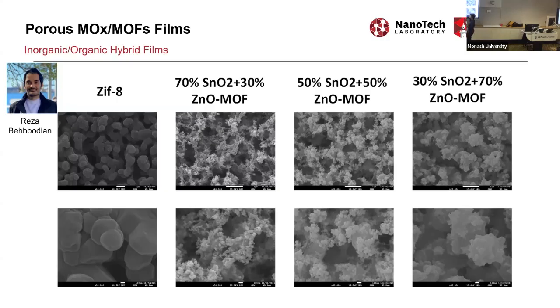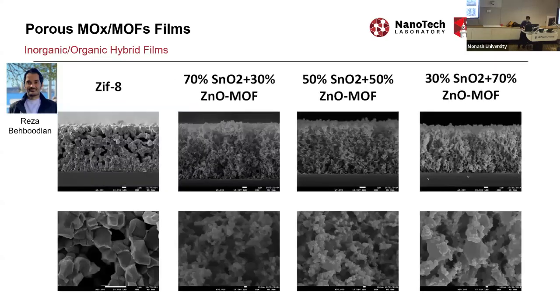So we created a zinc oxide, tin oxide composite. We expose it to the ligand, and only zinc oxide reacts with that ligand. So you end up with a tin oxide film which has big chunks of ZIF8 inside. And again, this is just one example. You can play with the metal oxide, you can play with the ligand, and do whatever suits you.